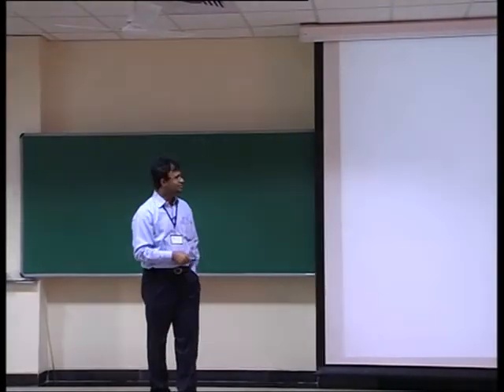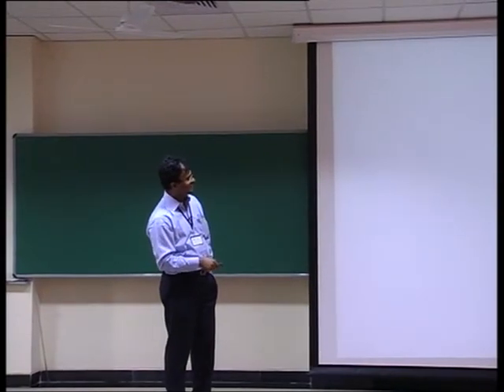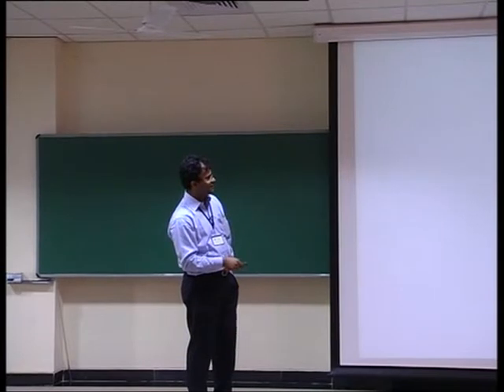In photoemission spectroscopy, we have to be really very careful, because there are many aspects that one needs to think of. Here you are exciting an electron from one electronic state to another, so the transition matrix element becomes very important when you are looking at the intensity of various features. Photoemission intensity is essentially directly proportional to the transition matrix element. At helium 2, if we calculate, we know that the 4f contribution in the photoemission cross section is much, much larger compared to helium 1. So you can attribute this difference to the larger photoemission cross section of the 4f states, and you can take the difference between these two and find out the 4f contribution.